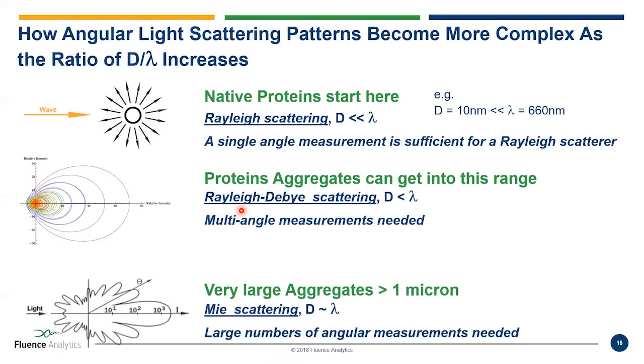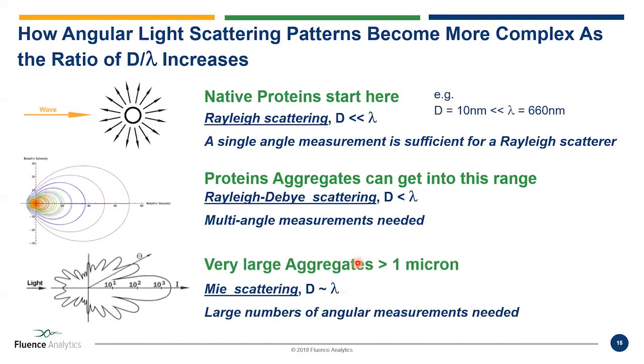And then as you get very large or you get into colloids, which tend to be more solid, you get into what's called Mie scattering, which is very complex, and you can see the pattern can be all kinds of things and have minima and maxima. That's usually not part of typical polymers, which are say a couple million and down. But for colloids of hundreds of nanometers on up, it's very important.